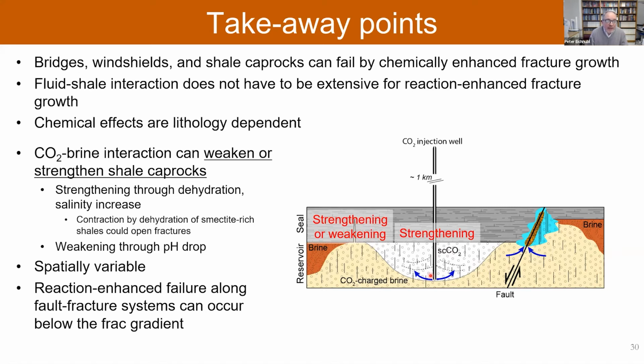The shale fluid interaction doesn't have to be very extensive for reaction-enhanced fracture growth, which is perhaps bad news because it would be hard to predict and hard to detect, right? So that's where what Catherine does with monitoring for CO2 at the surface or in aquifers, that's the way of handling this. Seismically, for instance, you would have a hard time monitoring this. And then understanding what those chemical effects are and how they are controlled by lithology, and maybe picking a sequestration site where the caprock is less prone to weaken under the chemical effects by the CO2 brine interaction, right? So we have seen that swelling clays may not be good.